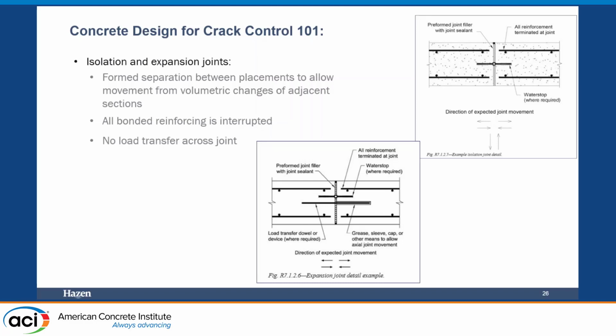The expansion joint has physical separate placement, bonded reinforcing is discontinued at the joint, but there are slip dowels that are cast in that allow movement in the plane of the joint, but prevent relative rotation of the two sections of wall. The walls can rotate, but the dowels will help to make sure that you're looking at the wall working together as one unit.